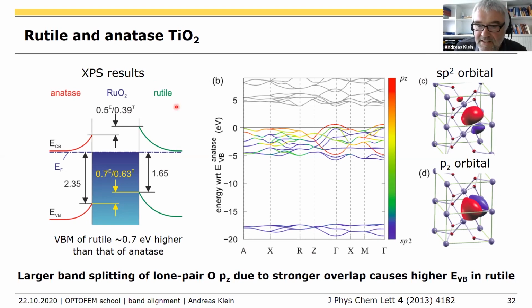What is different in the polytypes is the overlap of the non-bonding pz orbitals. So in rutile and in anatase titanium dioxide, the oxygen is sp2 hybridized. So it forms in principle a planar structure and all the bonding is in plane. The pz orbital is out of plane. Now in anatase and in rutile, the overlap between these pz orbitals is different. In rutile, you have a stronger overlap of the pz orbitals of neighboring oxygen atoms, and the stronger overlap gives a wider splitting of this band.